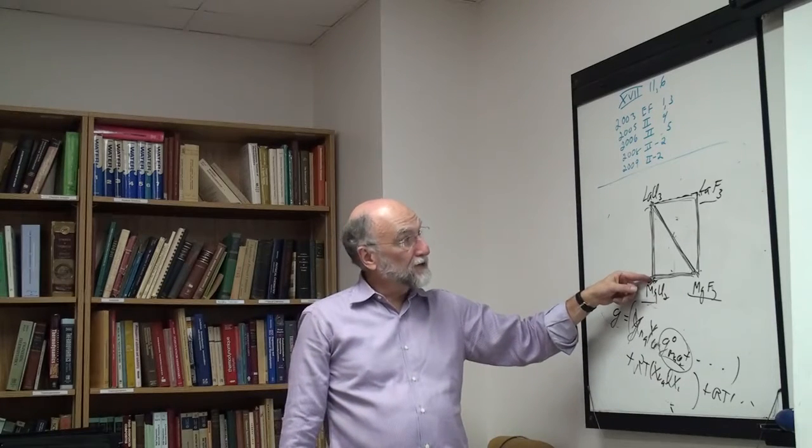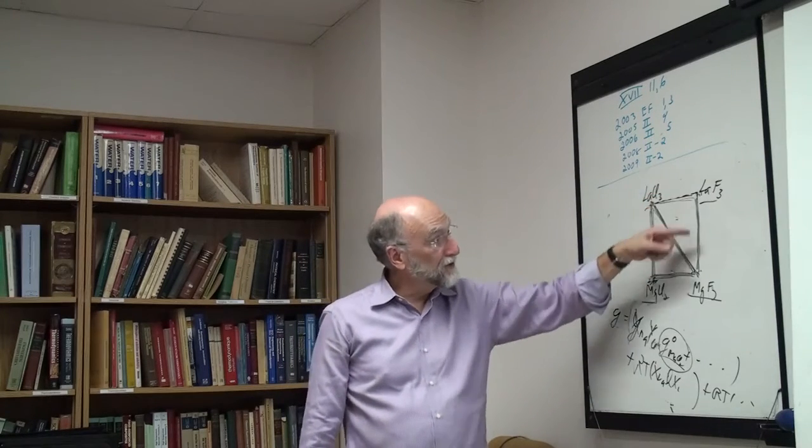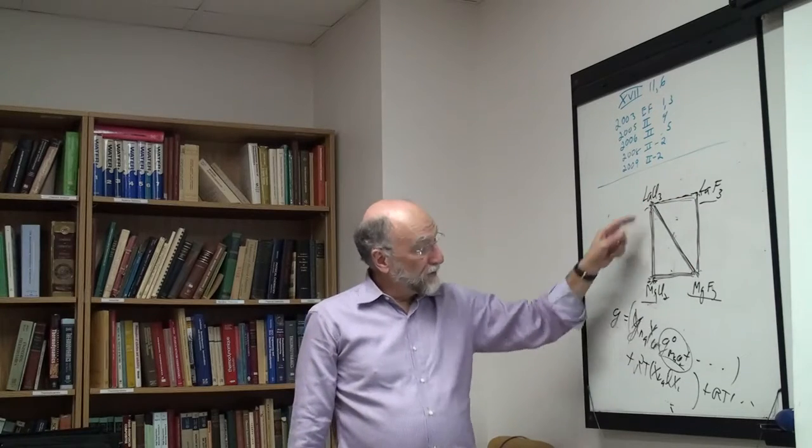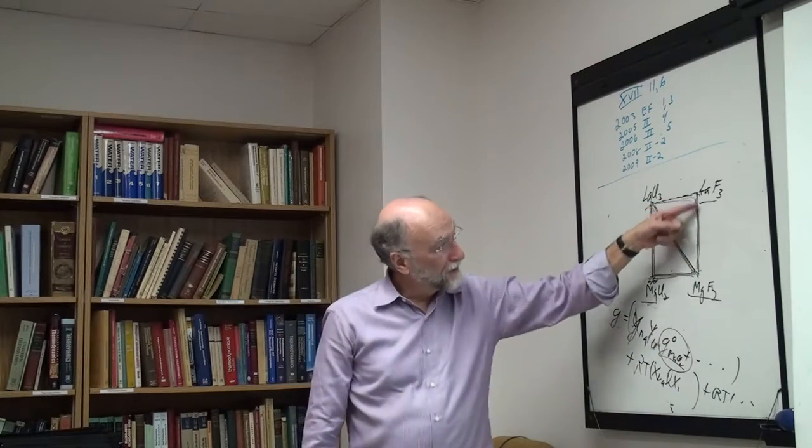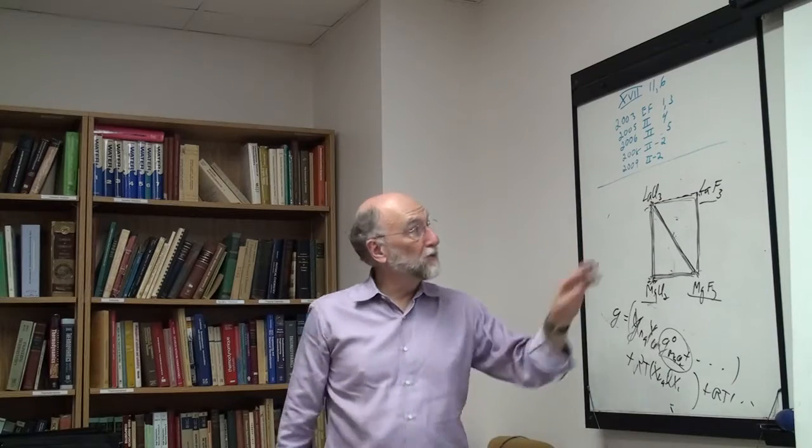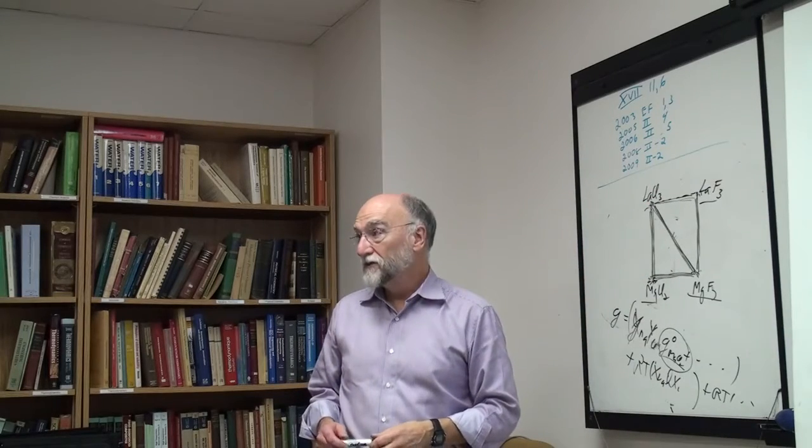But since it's a reciprocal system, that's not enough. You need the Gibbs energies of the 4 end members, so you can get the delta G of exchange, and you also need these binary systems over here as well, because they tell you the other interactions.